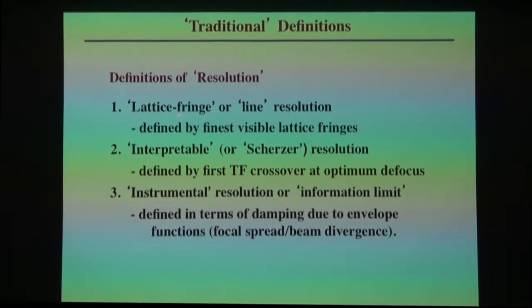The lattice fringe resolution is defined by the finest detail you can see in the lattice image. It doesn't tell you anything about where the atoms are. It tells you you have a very stable microscope and a very stable microscope environment. Traditionally, we have what is called the interpretable resolution, sometimes called the Scherzer resolution, and it's defined by the crossover of the transfer function at the optimum defocus. And these days, with aberration-corrected microscopes, we can push the resolution out to even higher spatial frequencies, finer and finer resolution, and in this case, the information limit depends on the envelope functions, either the focal spread or the beam divergence.